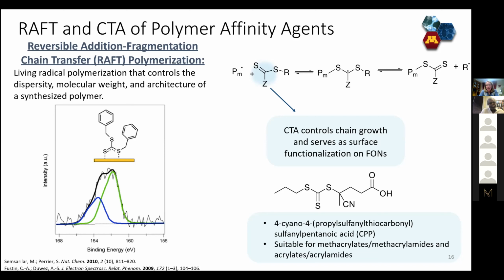I'll just say that in general, when you do a RAFT polymerization, you start with a molecule called the chain transfer agent, and that's what you see down here. And essentially, you introduce your monomer, and it's a controlled polymerization. So you can pretty nicely select exactly how many repeats of the monomer you're going to have.